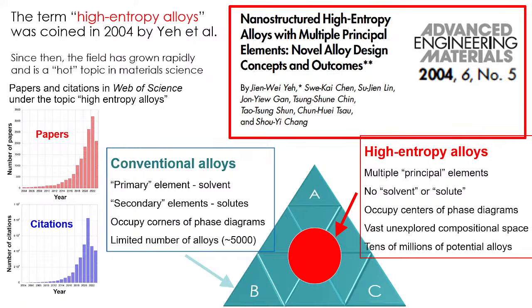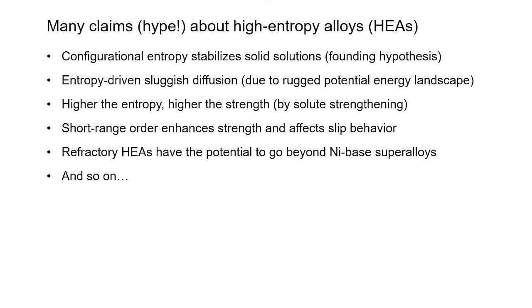And there are many claims, some might say hype, about high entropy alloys. The first is that configurational entropy stabilizes solid solution. This was the founding hypothesis of the field, Yeh's original paper. And then some people think that you have entropy-driven sluggish diffusion because of the rugged potential energy landscape. Some people have claimed that the higher the entropy, the higher the strength by solid solution strengthening. Most recently, short-range order has become the hot topic. There are dozens of papers on short-range order and how it enhances strength and affects fault behavior. And then finally, that some refractory HEAs have the potential to go beyond nickel-based superalloys and so on and so forth.